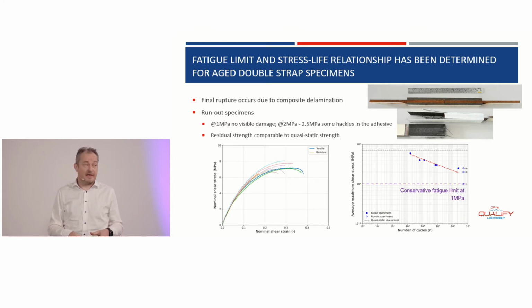And you could maybe think it is a little bit higher, but we analyzed this from a statistical point of view, and there is no significant difference in tensile strength between fatigue-tested specimens or quasi-statically tested specimens. So that means that for these stress levels at 1 megapascal, 2 megapascal, 2.5 megapascal, there is no real influence of fatigue on the adhesive behavior.